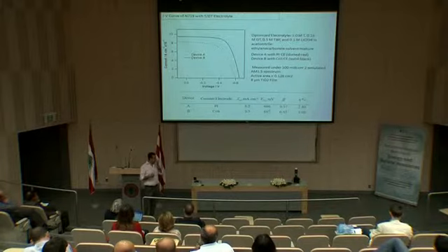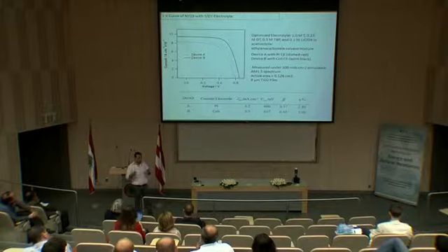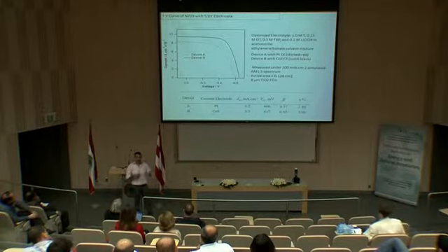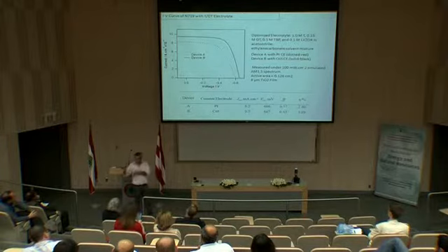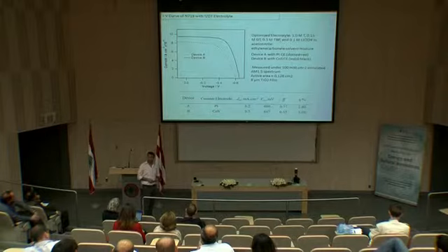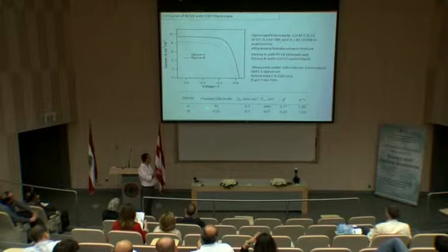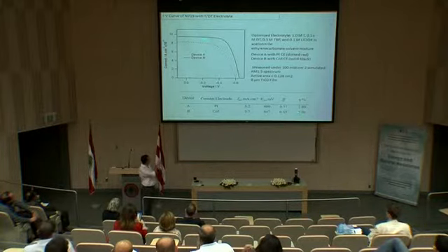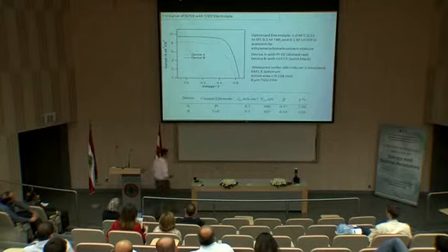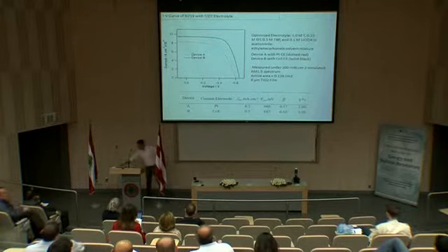That's the problem in the DSC field. When you change one parameter, the whole thing changes. So you have to work now not only with the electrolyte but also with the counter electrode. So we wanted to find a new material for the counter electrode. One of the materials that people use is cobalt sulfide, a thin film of cobalt sulfide. We tried this and the efficiency went much higher. It's this black one, up to 4%. But still, we should do better.